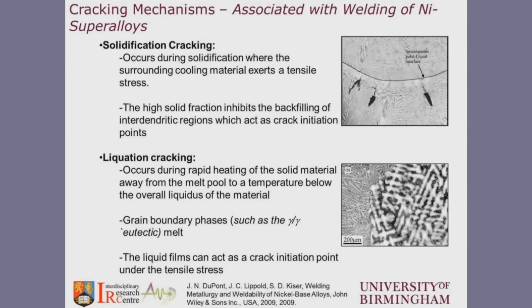So that's one thing that can happen in nickel superalloys with the complex chemistries we see inside them, that when we are basically building a component by additive manufacturing or even by welding, we are likely to get that mechanism of cracking. The second mechanism is called liquation cracking, and this can usually combine with rapid heating of the material, typically away from the melt pool.